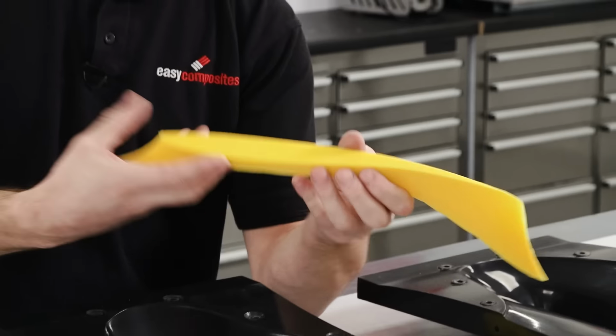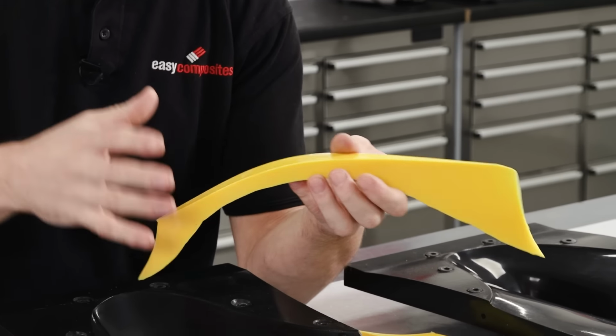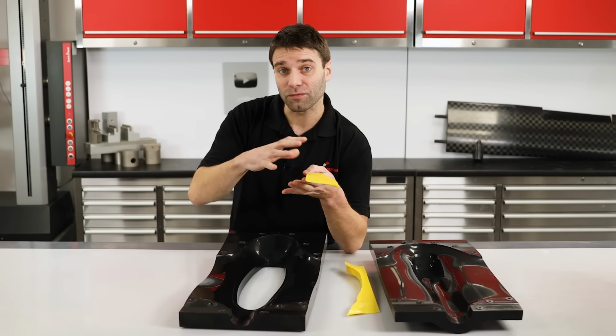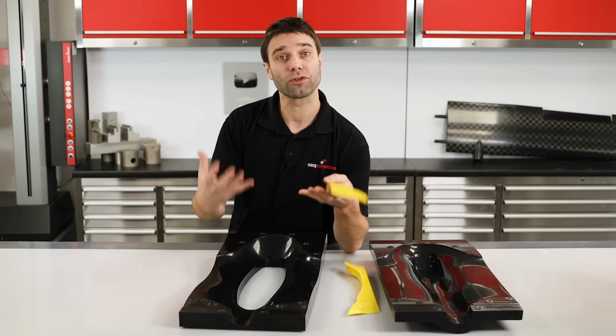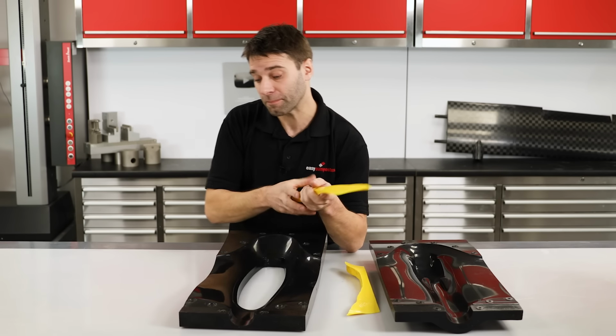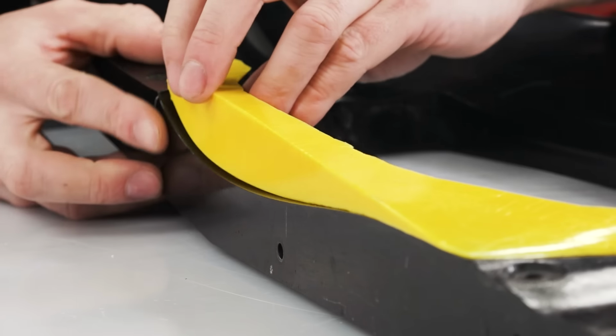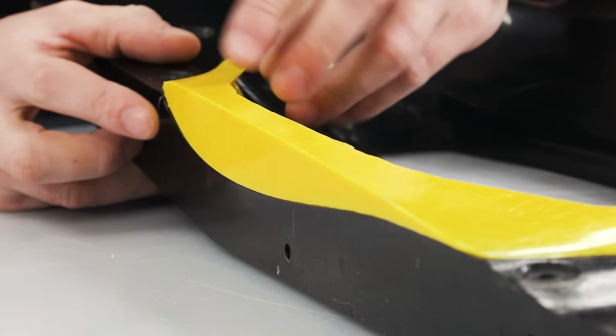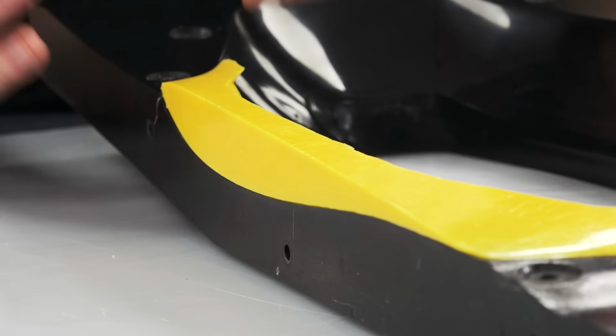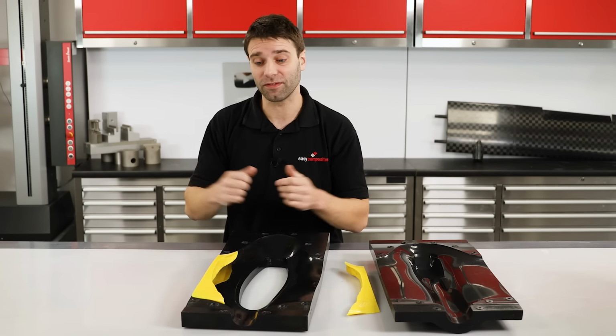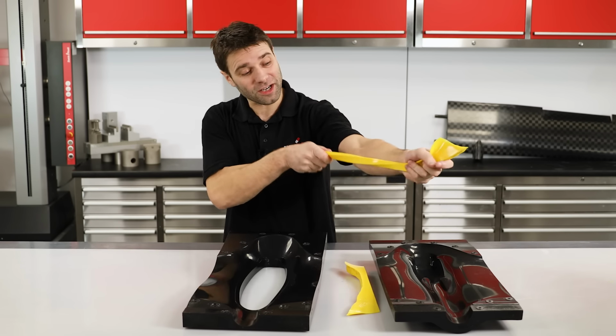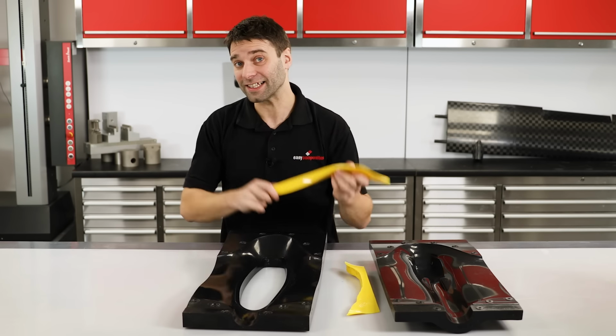Being a 40 Shore A hardness, they are very flexible, and that's really helpful as it allows them to conform that little bit under the vacuum and properly consolidate the laminate underneath. They also very accurately follow all of the sharp shapes and contours of the mould, meaning that our bag won't have to go into those areas in the final cure. And being incredibly strong, these things are going to last indefinitely.